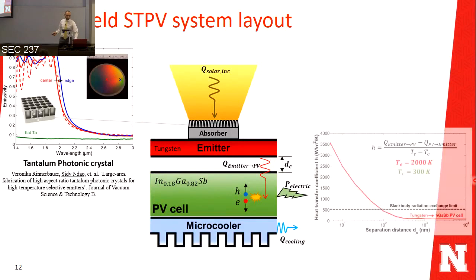So that's a normal solar thermophotovoltaic. If you need to make a near field solar thermophotovoltaic, you need to decrease this separation distance to very small values. So this curve will make you appreciate why near field thermal radiation might be interesting for these kinds of devices. That's the separation distance between the emitter and the PV cell, and that's the heat transfer coefficient between them. You notice that from the tungsten to the indium gallium antimonide PV cell at far field, the heat transfer coefficient is kind of low. Decreasing separation distance increases the heat transfer coefficient exponentially, and it can even exceed the black body radiation. So you should expect from these systems to have higher energy density than usual systems.